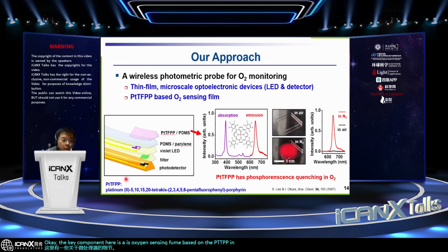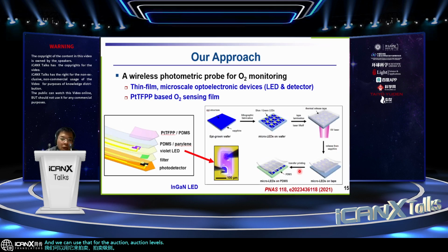This PtTFPP is a platinum-based complex, and this molecule has an absorption peak in the violet region around 400 nanometers, and has an emission in the red region around 650 nanometers. Also, this PtTFPP shows phosphorescence quenching in oxygen, which means that this red emission intensity is very strong in a low oxygen environment, and we can use that for low oxygen level sensing. And to excite this phosphor, we use a violet LED as a light source.